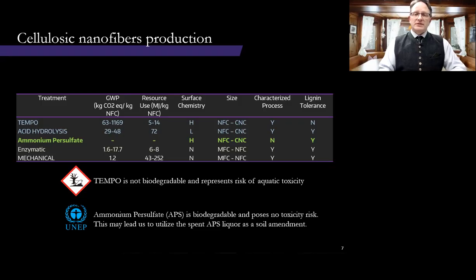Of all the chemical treatments, acid hydrolysis is the only commercially scaled process to date, but it has some limitations. It's limited in the surface chemistry it can develop. It has environmental disadvantages, and it is also one of the higher energy demanding processes. Of all those chemical treatments, TEMPO is the most well documented in literature. Unfortunately, it is the most toxic, and it's not biodegradable. It also has the added limitation of not being tolerant to lignin. But it can develop a wide variety of surface charges, and it gets us down into the nanofibrillated cellulose and crystalline nanocellulose region.